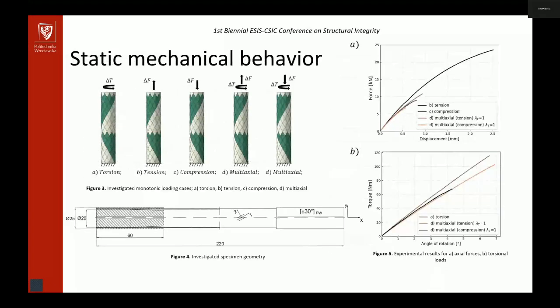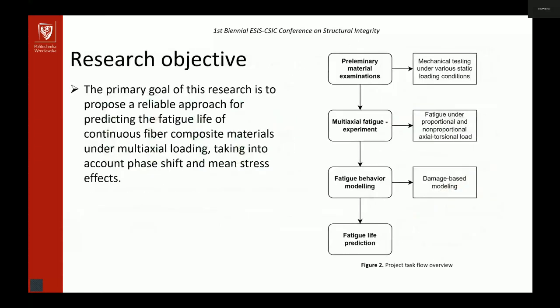composites, we can see that there are two coordinate systems. The first one is a global one, which is the laminate coordinate system. In this case, X is the direction of the axial force and Y is perpendicular. But if we consider composites, we rather use the material coordinate system for one lamina, denoted 1, 2, 3, where 1 is the direction along the fibers and 2 is perpendicular. You can see on the right side the results from the static investigation.